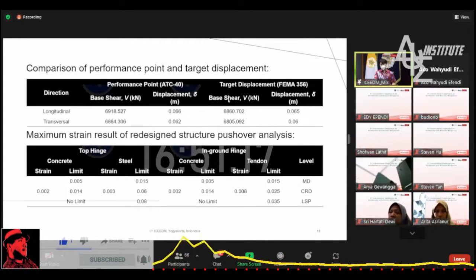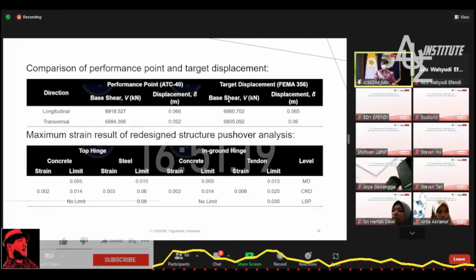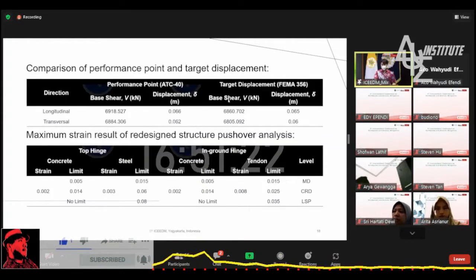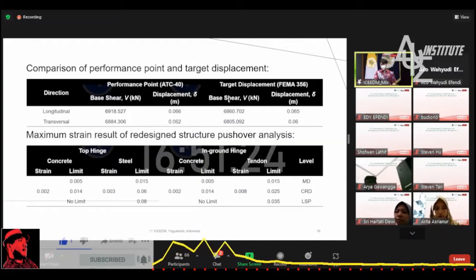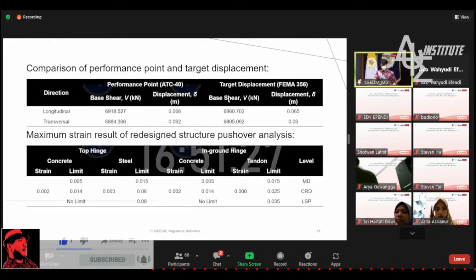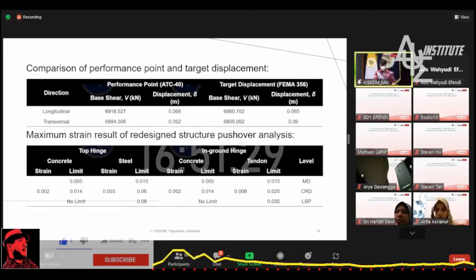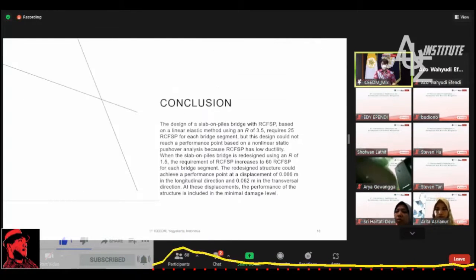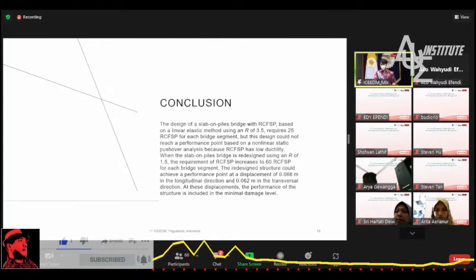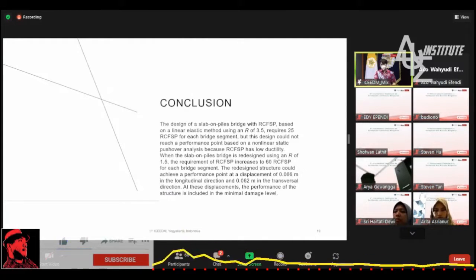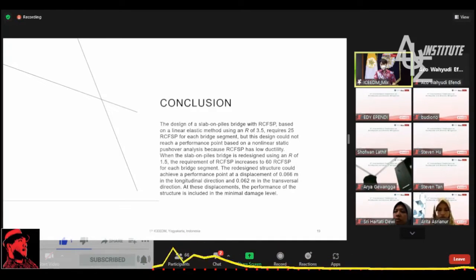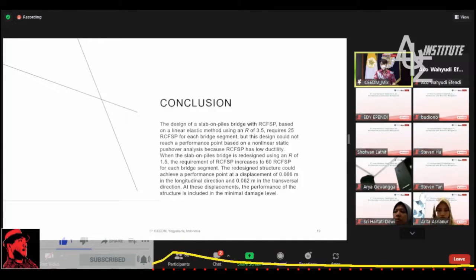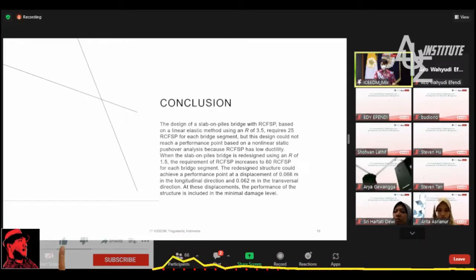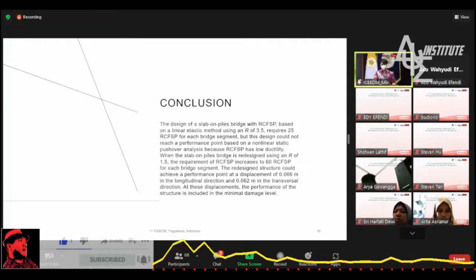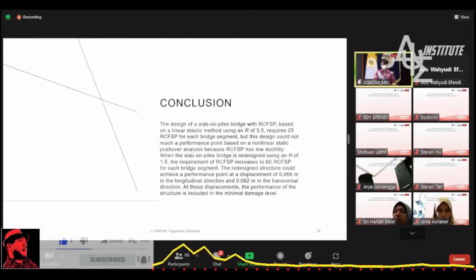And so globally, the redesigned bridge structures are at the condition of minimal damage also. And finally, the conclusion we get from this study is the design of slab-on-pile bridge with RCFSP based on a linear elastic method using an R of 3.5 requires 25 RCFSP for each bridge segment, but this design could not reach a performance point based on a nonlinear static pushover analysis because RCFSP has low ductility.